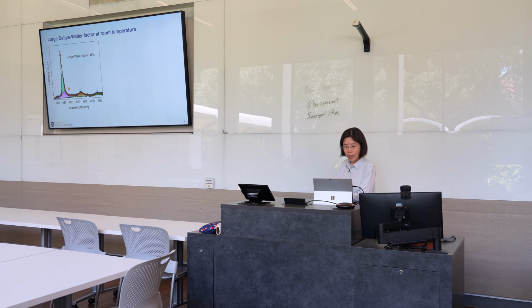So now if you look at the photoluminescence spectrum, you can see there's a sharp peak. There are also some shoulders and some small peaks over here. The sharp peak corresponds to the zero phonon line, and these small peaks correspond to the phonon sideband and also the second order phonon sideband. You can also see there's a small shoulder here corresponding to the LA phonon of boron nitride.